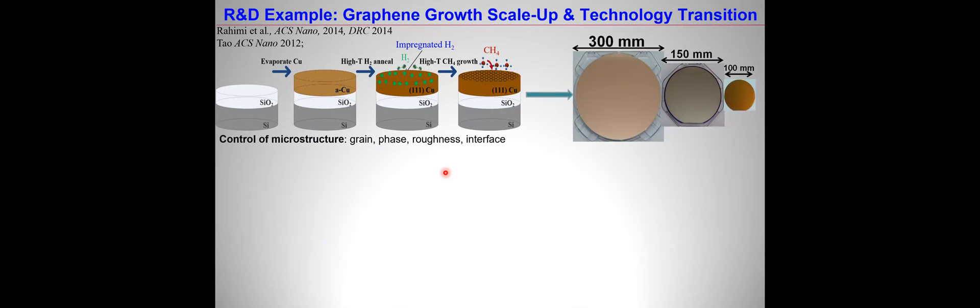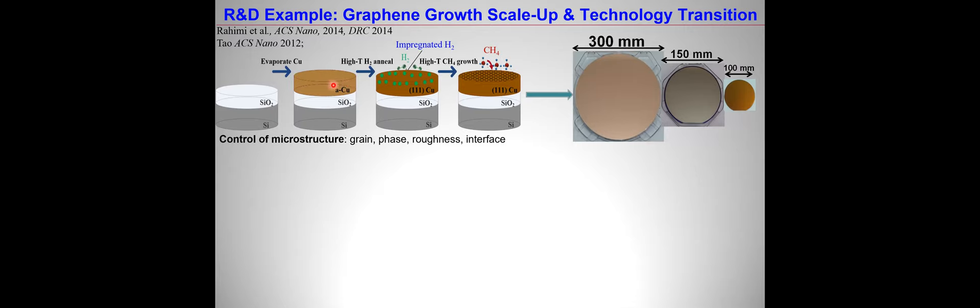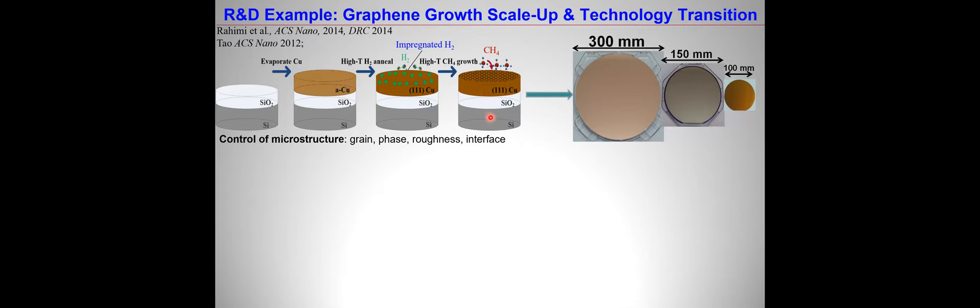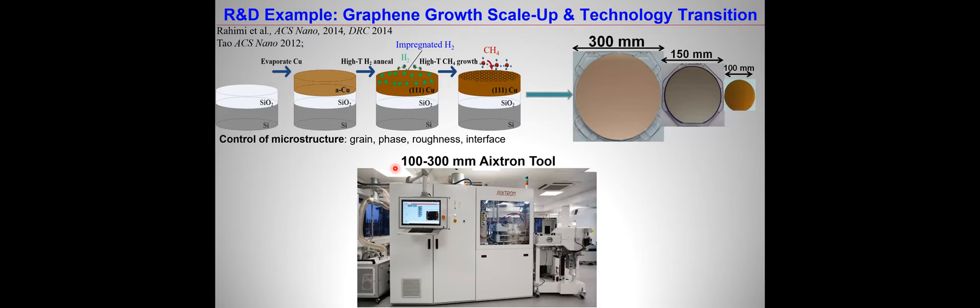Let me give some examples of work we have done in my lab in the last 10 years or so. We started working on the growth of graphene about 10 years ago. We developed a method of growing this based on previous work by my colleague Rod Ruoff, where we could grow this on catalytic copper films on silicon wafers. The main innovation was we needed to control the microstructure so that we can grow these crystalline materials by chemical vapor deposition on a relatively nanocrystalline catalytic copper film on a silicon-based wafer. We were able to scale this from 4-inch wafers to ultimately 12-inch wafers in partnership with Aixtron.